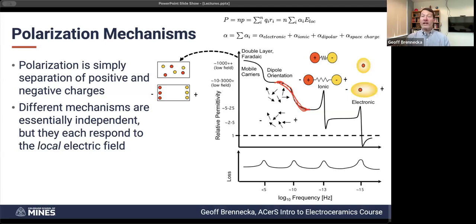There's no spring that when we align the dipole in this direction and then we remove the field, yeah, it's fine. It was perfectly happy. It was a permanent dipole, so it didn't really care if it was this direction or that direction or this direction. So what is it that's going to lead to reorientation of those dipoles after we get rid of the electric field that's forcing them to be lined in some way? It's really just thermal energy. So disorder associated with thermal energy is going to cause those dipoles to relax and eventually go back to being random. And so this behavior is represented as a relaxation rather than a resonance.